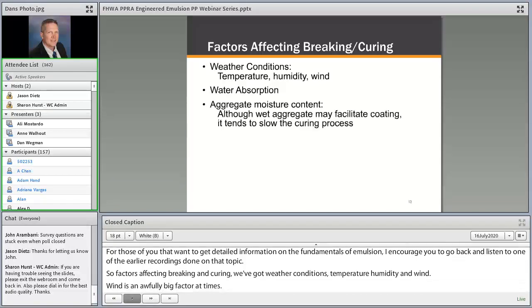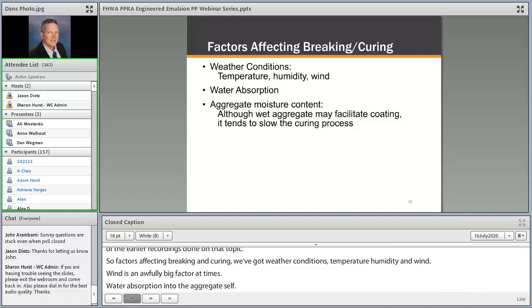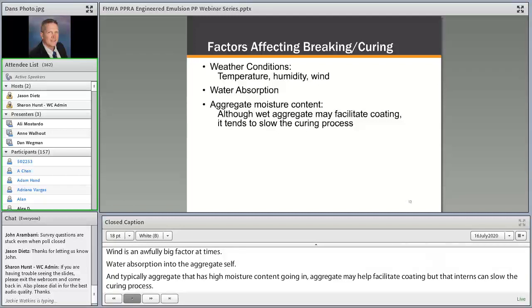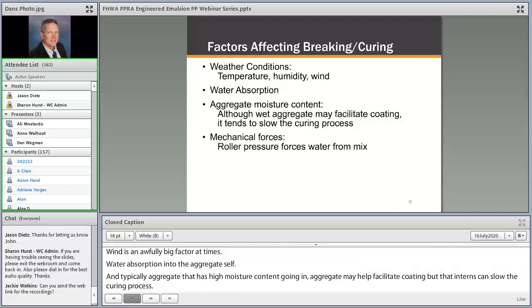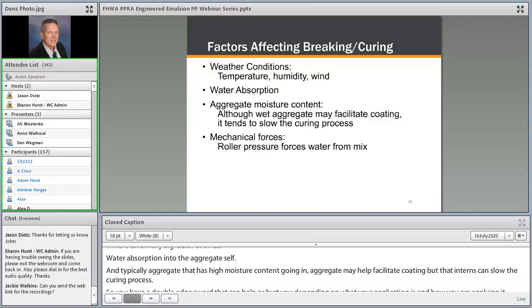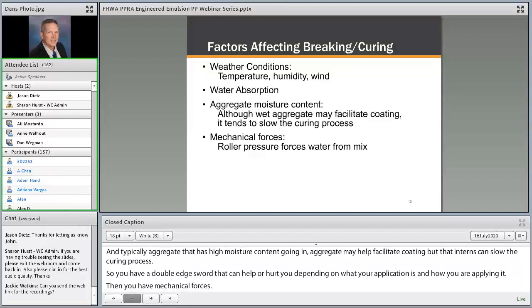Typically, aggregate that has high moisture content going in, wet aggregate, may help facilitate coating, but that in turn can slow the curing process. So you've got kind of double edges of a sword there that can help or hurt you depending on what your application is and how you're applying it. And then you have mechanical forces. So any operation that's using compactive effort or rollers to compact the material, you're also forcing water from that mix and assisting in the curing time with that activity as well.